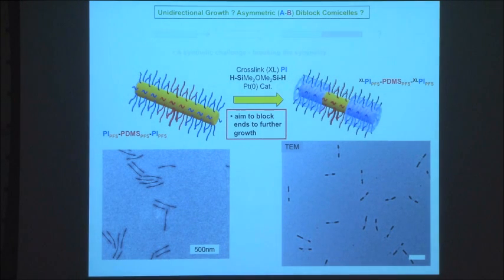And our thinking here is that the ends of these cylinders, the polyisoprene chains, should spend some time in front of the faces here. And this is a reversible process unless you cross-link and fix it in to block the ends. So what we're hoping is we've blocked the ends of these structures. So that's the aim, and you can follow this by electron microscopy. So this is the TEM of the tri-block comicelles here. Once you cross-link the polyisoprene end coronas, you can visualize them very easily in the electron microscopy.